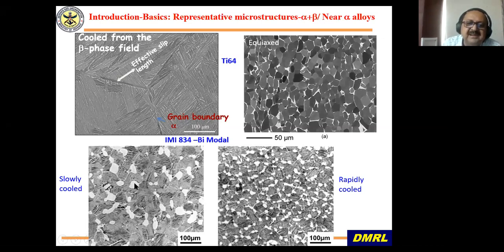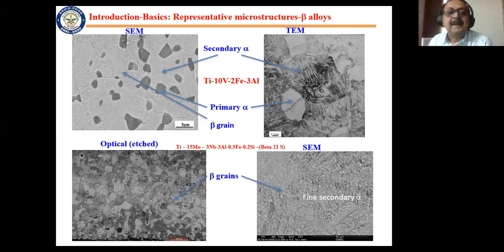So here it is a combination of this alpha phase, which is shown here, and the transformed beta. But the grain sizes are much finer. Similarly, when you cool differently, you get a much finer structure. So these are used for applications which see both creep as well as fatigue. Then coming to beta alloys, as I told you, they can retain the beta phase, but the alloys which are metastable beta alloys are normally used in alpha plus beta deformed, solution heat treated, and aged condition.